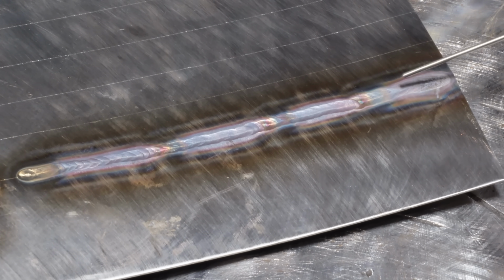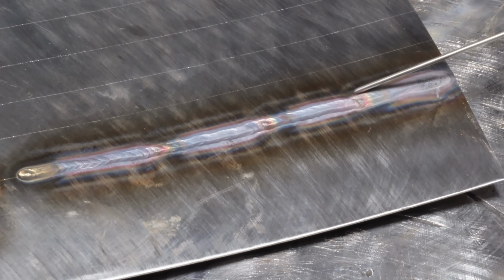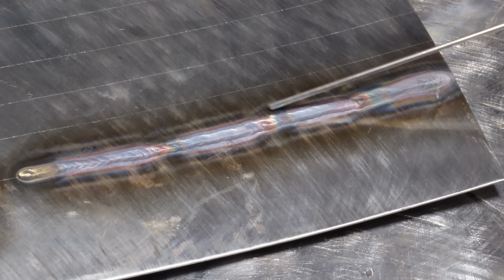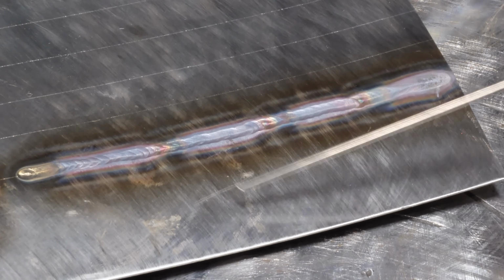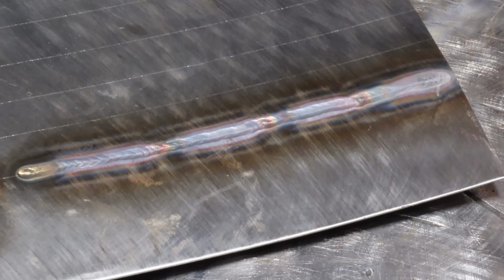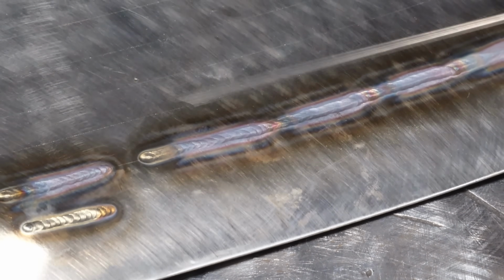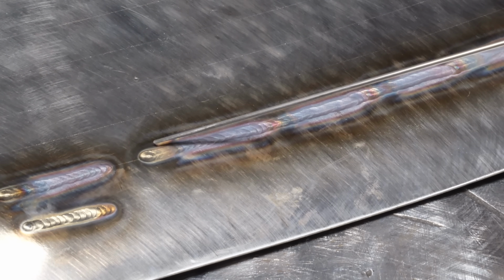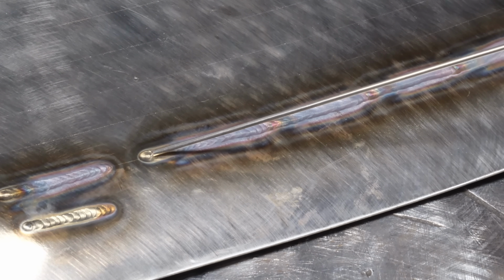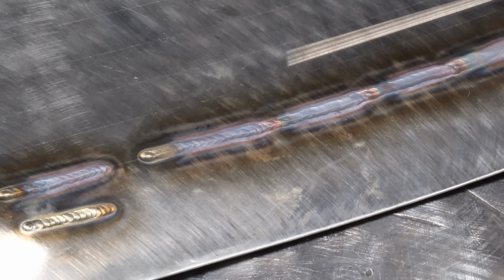Now, one of the things I did do right on this is, if you notice at the termination, the end of every weld, how it's more or less silver gold, especially down over here. I'll move that so you can see it. That's a good sign. That means I'm holding my post flow there long enough that as it cools, it doesn't react with the oxygen and form oxides.